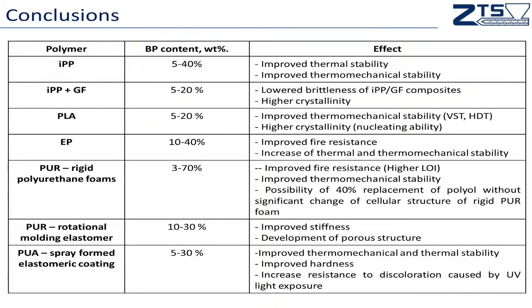Usually when we incorporate 20 or 30% of silica or various fillers into polymer materials, the processing of those materials is really weak. So the processing properties are strongly suppressed. In this case, this phenomenon did not occur. So we can achieve a composite with more than 40% replacement of the polymer, but with processing properties that are comparable to unfilled materials. So this is really important from the application point of view.